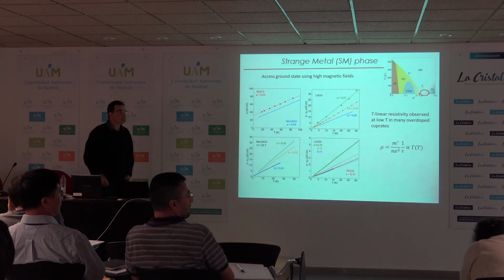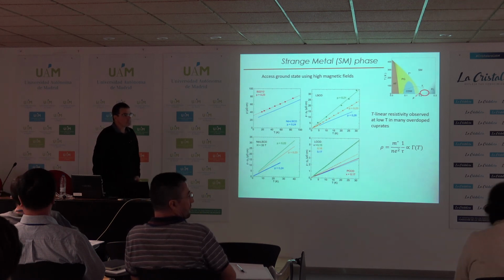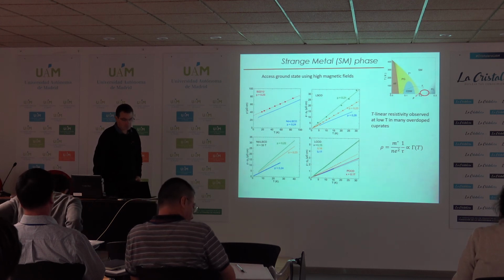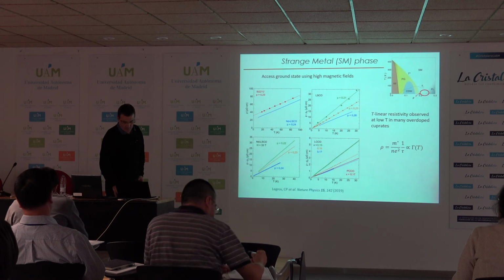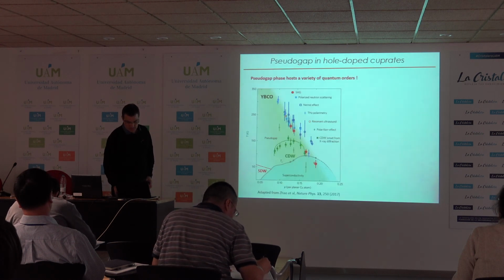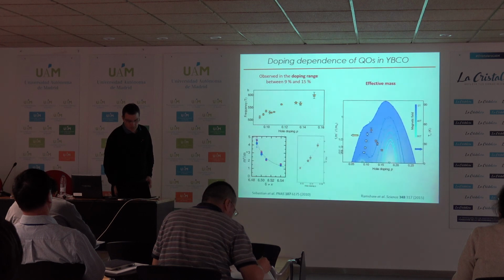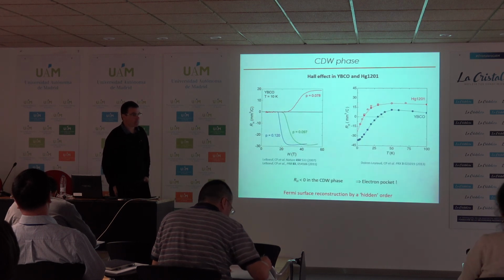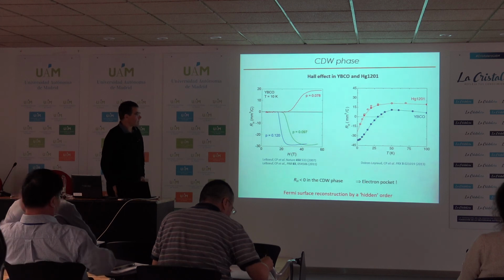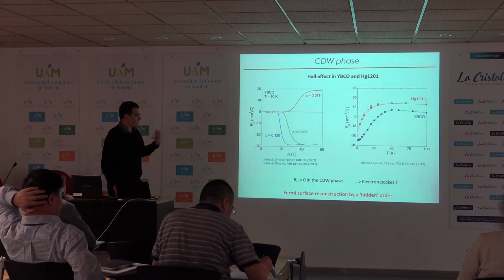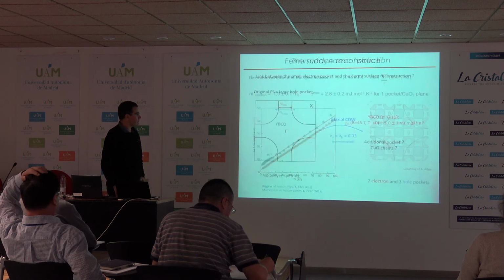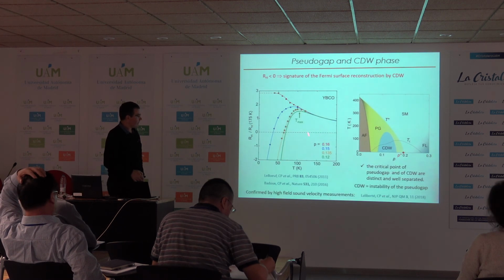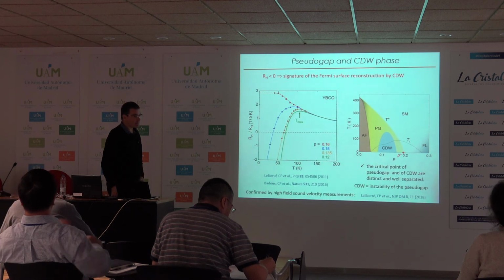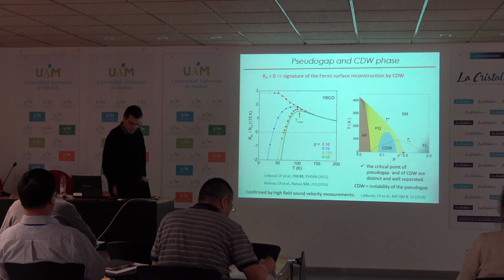Other questions? Yes. So again, how do you determine that the pseudogap and the charge wave critical points were different? So it's from Hall effect measurements. The signature of charge density wave is a negative Hall effect coefficient. And in fact, when you go above 15%, you measure that the Hall effect remains positive down to the lowest temperature that we have reached.